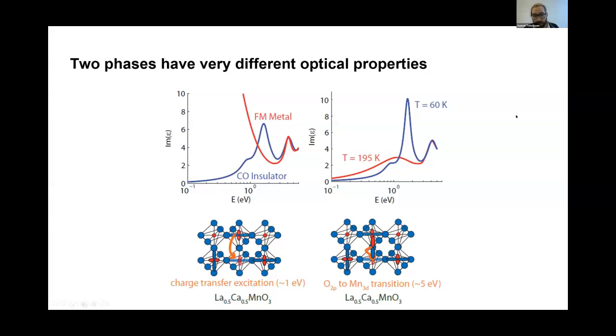So on the left here, I've shown the ferromagnetic metal, and this is the imaginary part of the dielectric constant. So this is the absorptive part. And here's the charge-ordered insulator. The charge-ordered insulator has a peak in the conductivity around 1 eV, and the ferromagnetic metal has this large Drude peak that goes to large values at 0 frequency. And in the charge-ordered insulating phase, this peak also redshifts and disappears at higher temperature. So this peak here is indicative of charge ordering. And what it is, is intersite charge transfer.